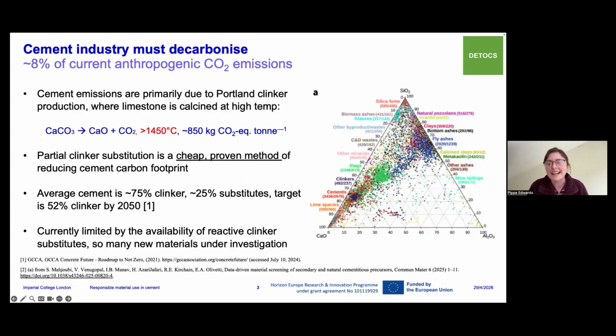But the way we make clinker is we heat limestone with siliceous materials at high temperature. This process releases CO2 both from the chemical reaction, which is difficult to abate, and from fossil fuel combustion. So it's about 1450 degrees in the kiln. Producing 1 ton of clinker has a carbon footprint of about 850 kilograms of CO2 equivalent.